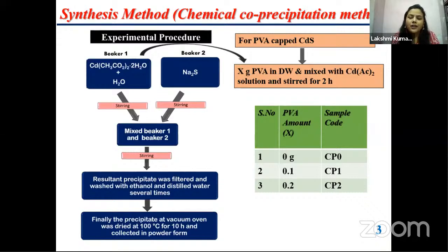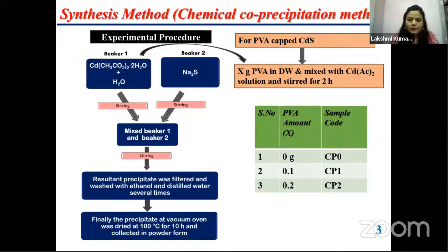For capping, I have done the same process. Just I have added an appropriate amount of polyvinyl alcohol for capping just before centrifuging it, and these are the compounds and the amounts which I have added here: 0 gram, 0.1 and 0.2 gram. And these are the sample codes which I have used for the samples for further analysis.